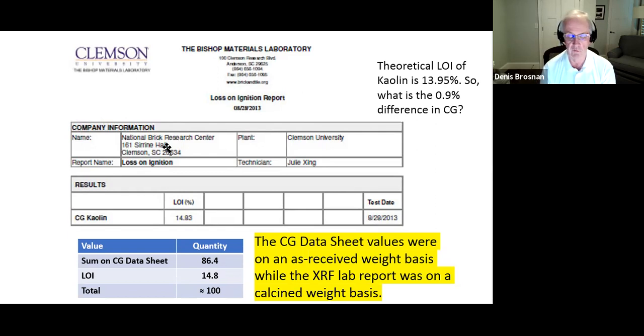And as you'll see as we go along, kaolin will in fact lose hydroxyls as water vapor as it's heated up to below 1,000 degrees Celsius. So the theoretical loss on ignition of kaolin as a mineral is 13.95%. In this particular case with the CG kaolin, you can see that I came up with a number of 14.83%. So I came up with a little higher loss on ignition than theoretical kaolin. Well, the actual product probably contains a little bit of carbonaceous matter. There could be some other minerals present in minor percentages that lead to a little weight loss. So we're just slightly higher.